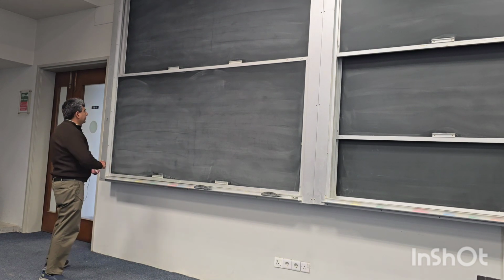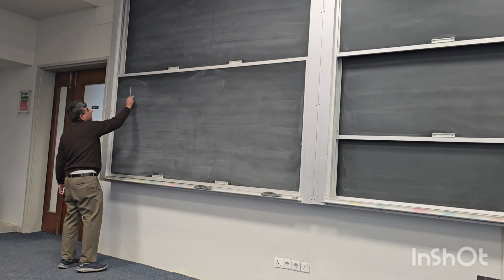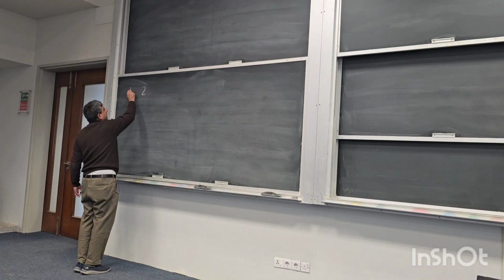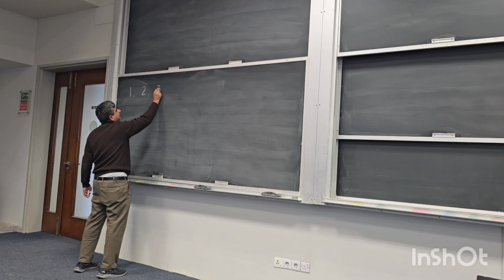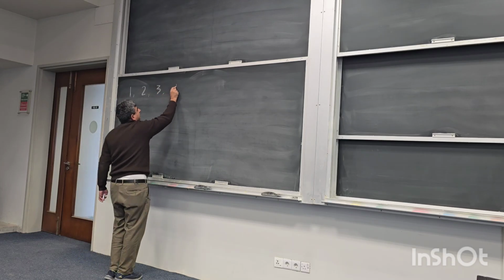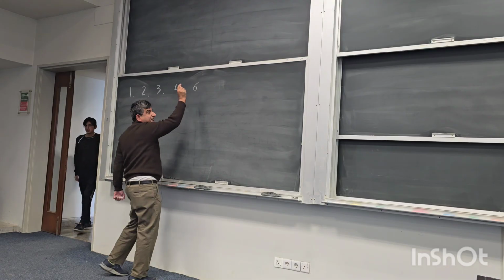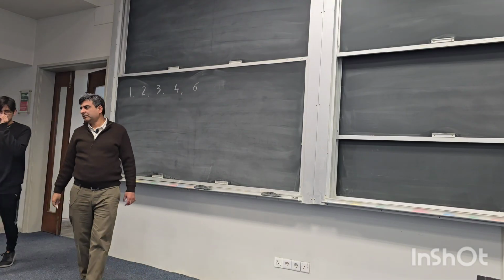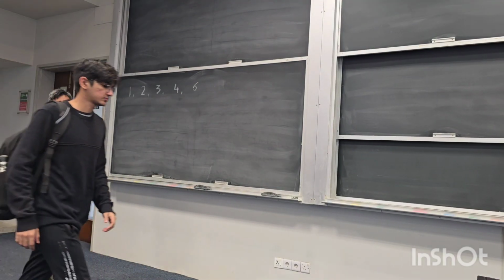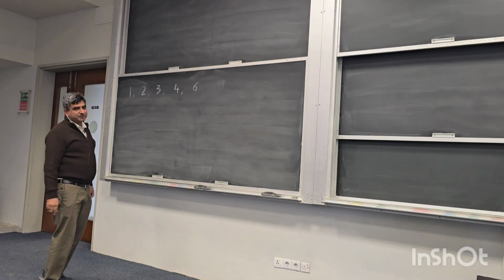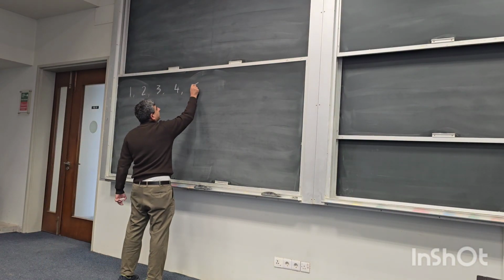And what are the point operations? They are 1, 2, 3, 4, 6. We do not have a 5-fold rotation in solids. In molecules we may, because there is no restraint in a molecule. A molecule can have 5-fold symmetry, but not a solid. 6.